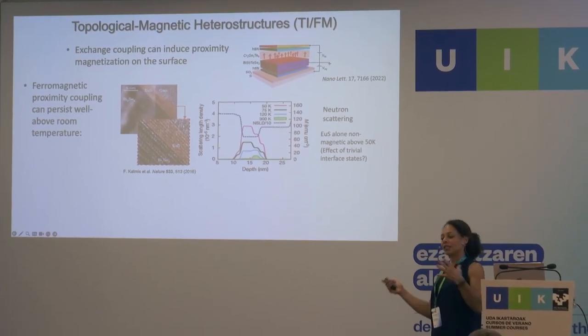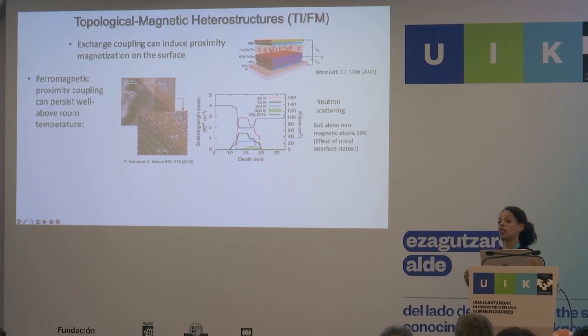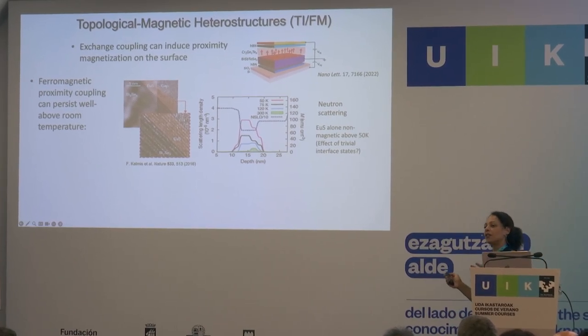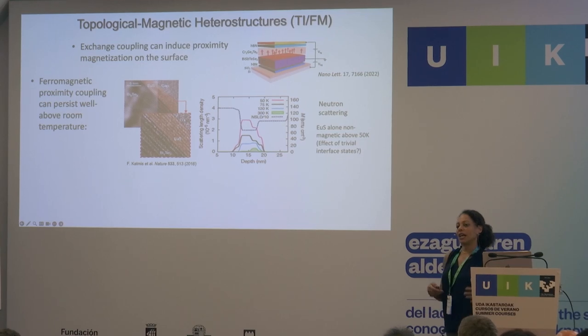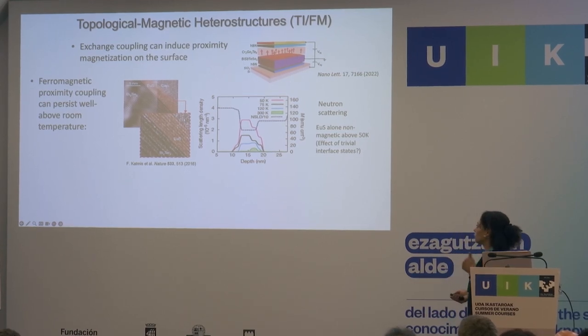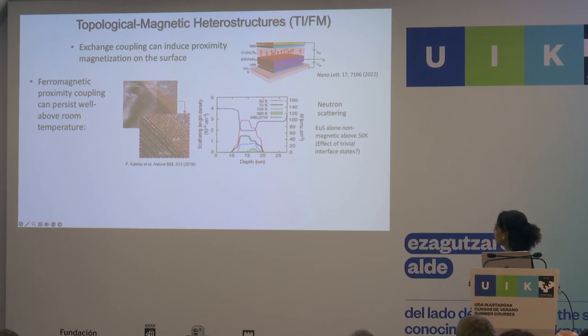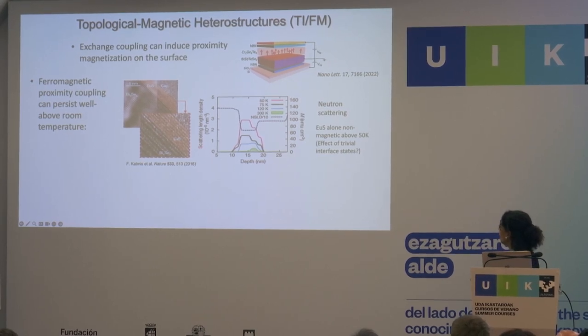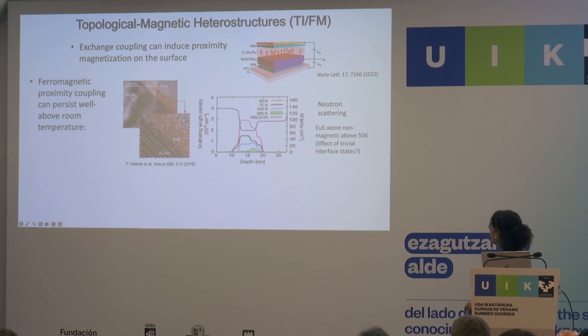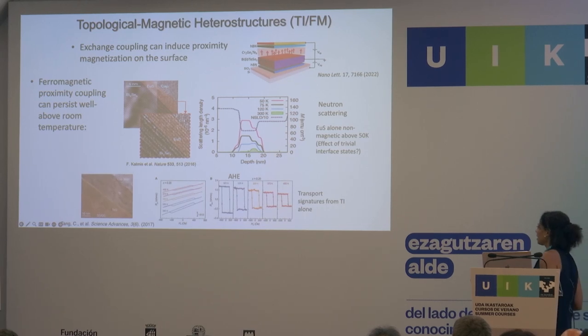Right? So one of the problems we said about the quantum anomalous Hall effect is it only occurs at low temperatures, and at least here there's a possibility that this sort of magnetic surface persists all the way up to room temperature. This has been shown in these nice experiments here on bismuth selenide and europium sulfide with neutron scattering. This experiment was a little bit complicated to interpret, but it did show evidence of room temperature ferromagnetic coupling.